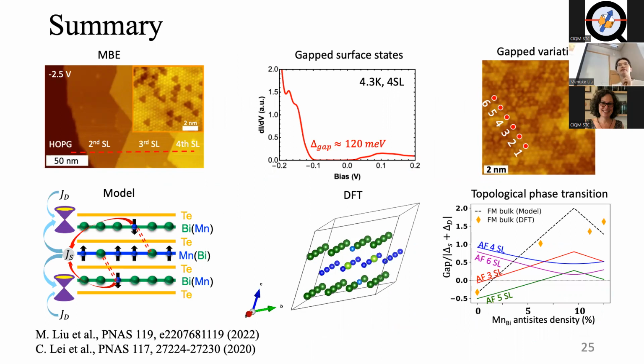Right. Go ahead. So when you do the growth of this material, do you do the full co-deposition of all three elements, or do you use a shutter to control it, so you first grow the bismuth tellurium layer and then the manganese tellurium layer? How do you do that? Can you actually alter the surface that you terminate with? Can you terminate it with a manganese tellurium layer?